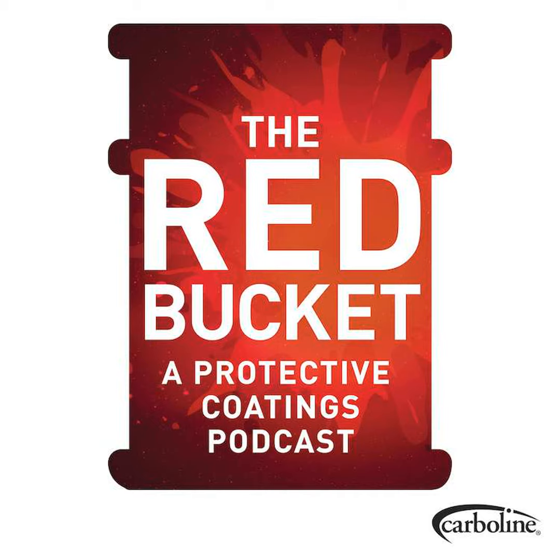Correct. It was observed that some areas of that substrate should have been blended. They weren't, but they could have used it. And upon inspection, we were amazed at what we were seeing. I mean, there was no deterioration of the coating in those sharp edges. There was no cracking that you would see and experience in those knuckle areas from transportation and the service that it goes into.